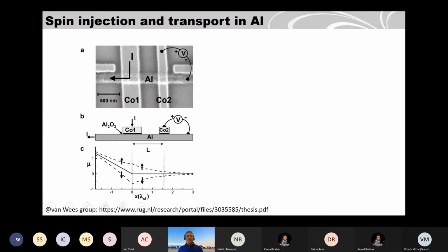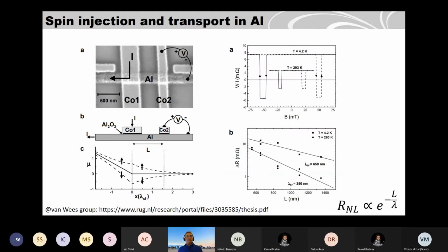And then at some point within the spin diffusion length, you put a detector ferromagnet, which is a second cobalt here, as you see in the picture. So that can detect the spin you created in aluminum. So how to detect that? Because you can switch the magnetization of these two ferromagnets independently. They have different widths, so different coercive fields. So you can apply a different field to switch them independently.